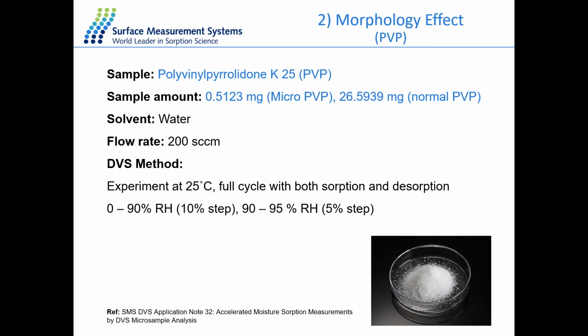Since this is a very hygroscopic sample, and the balance inside the system has very good performance, with a resolution of 0.1 microgram, even when the sample mass is less than 1 milligram, we can still get reasonable data and a good comparison between different masses. So here we call the half milligram sample the micro PVP sample and the other sample the normal PVP sample.